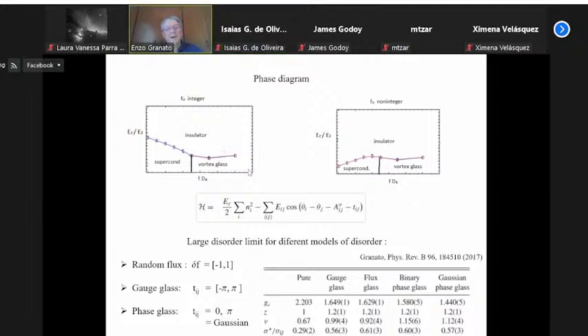So the phase diagram is taken for this phase here, and from the left it is for the interacting case, and on the right for the non-interacting case. They are qualitatively similar. There are three phases: superconductor, vortex glass, and insulating phase. The notable difference is for small disorder, in which for the interacting case the critical property decreases with the disorder, whereas for the non-interacting case it increases with the disorder. But they both mirror that same property.